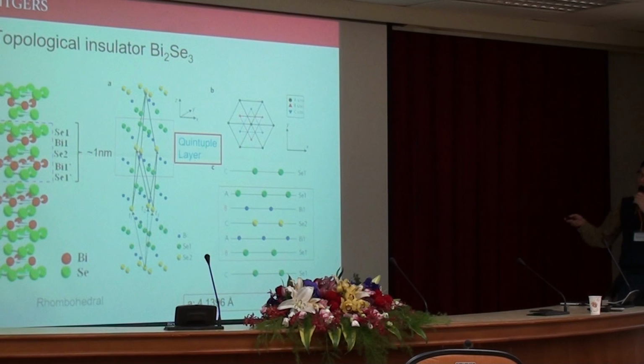So, okay, bismuth selenide. I said that bismuth selenide is one of the most famous topological insulators, and the structure is a layered structure. Bismuth selenide is composed of 5 atomic layers, bismuth to selenium 3, and between those layers there's van der Waals bonding. This minimum unit is called a quintuple layer, and the acronym is QL. That is commonly used.